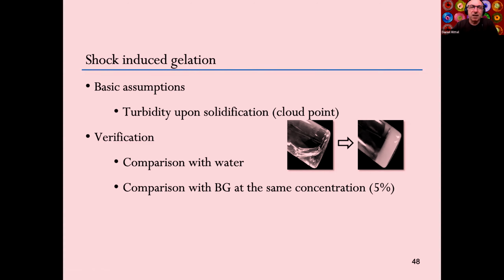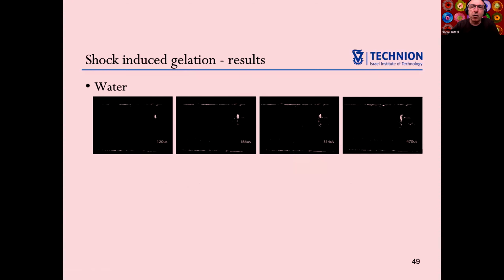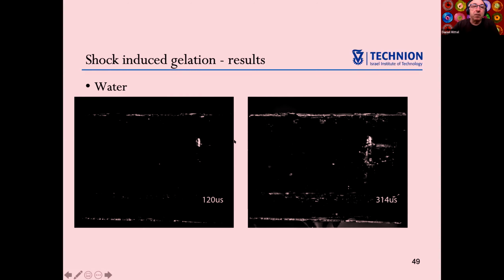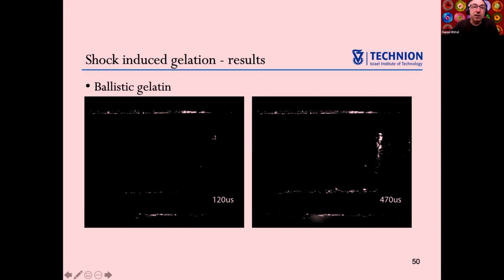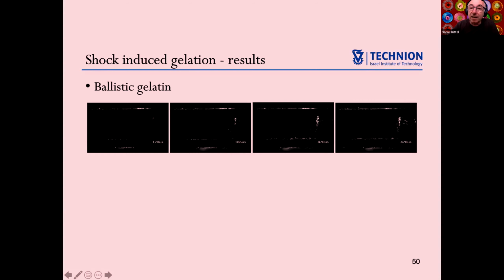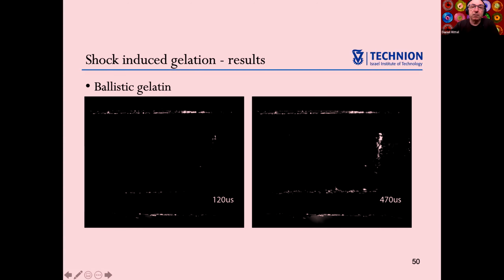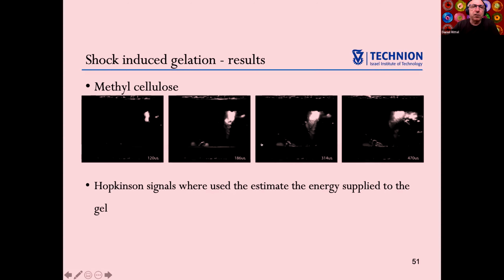I'm almost done. We compare with water, we compare with ballistic gelatin, and then we go to the gel. Water, at various times, nothing. You see, nothing happens. Ballistic gelatin, you look, nothing, with time, nothing. You go to the methyl cellulose gel, and here you're surprised. You see a white blob here, close to the impacting bar. That would indicate solidification.